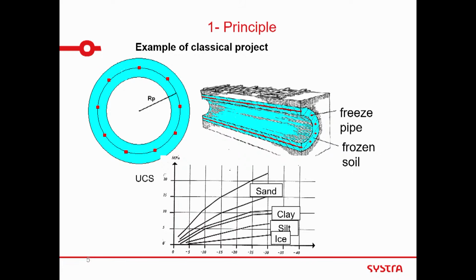What is important, just to give figures and you know where we are going, is a kind of UCS, so unconfined compressive strength of this material at the end. This is in MPa, so directly we can see it. You see, for example, in sand, usually we freeze at about -10, the soil. The fluid is at -30, but globally the soil is at -10, -15. The strength, UCS, is in the order of 7, 8, 10 MPa for sand.